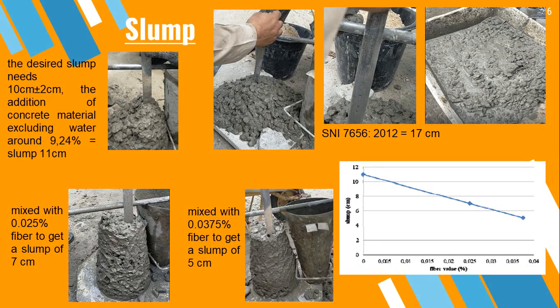For the slump result, the desired slump needs to be 10 centimeters plus or minus 2 centimeters, and we get a slump of 11 centimeters. After mixing with fiber at 0.025%, we get a slump of 7 centimeters, and with 0.0375% fiber we get a slump of 5 centimeters. So the slump decreased in the final result.